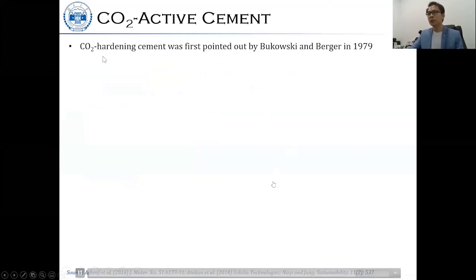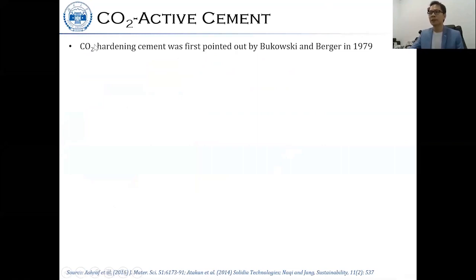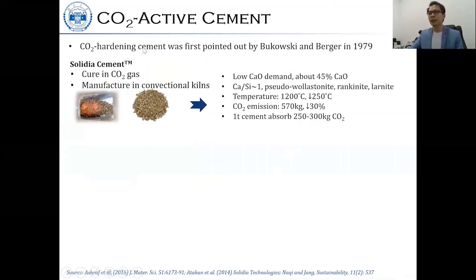So this has also been pointed out in 1979, using CO2 to harden the cement. And by the Solidia technology, they have manufactured this novel cement using low calcium oxide. In turn, they can reduce the sintering temperature down to 1200 and also reduce the CO2 emission by 30%. So they use the CO2 to cure the cement instead of water for the hydration, so it is able to absorb 250 to 300 kg of CO2 for 1 ton of cement.